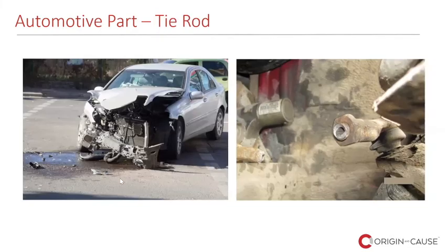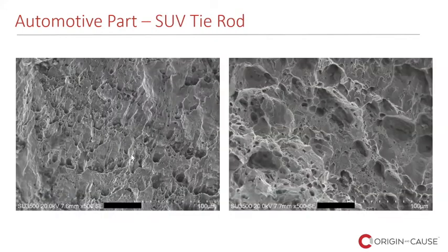The most important piece of evidence was on the fracture surface itself. These two images taken under the scanning electron microscope show features called dimples. Dimples are always associated with ductile overload. In other words, the tie rod fractured because of overload. It was subjected to some sort of stress. And it did not fail as the result of a manufacturing defect.